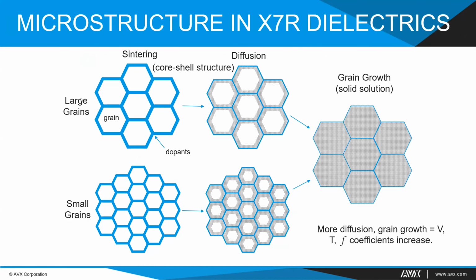Microstructure in X7R materials looks a little bit like this. They follow what we call the core shell model, if you will. And what that means is usually we have a high purity grain of material that is surrounded by a sort of melange of dopants, if you will, that sit here. And although it looks like they form a grain boundary phase, what that actually represents is the outer layers of the grain that tend to dope, and they create a composite structure right within the grain itself. There's relatively little on the grain boundaries that are important to this discussion. And as you can see, with smaller grains, we might have more of that material present, or we might have the same amount of material distributed over different area. And so the amounts of dopants that we use in these things can be very important.